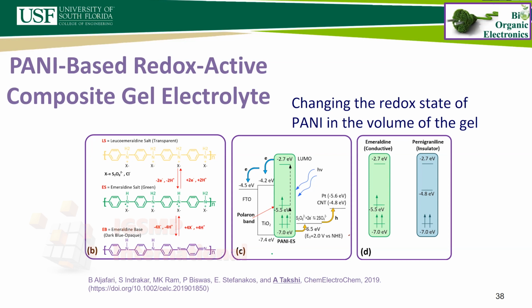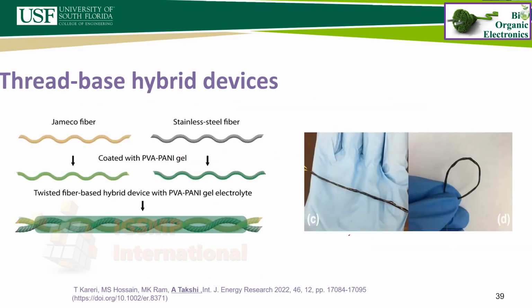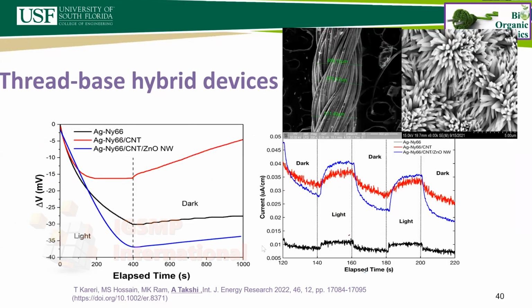So we took advantage of such a feature and said that perhaps we can use it for making wearable hybrid devices. We took that gel and chose 2 different types of conductive threads. We coated them with the gel, and then we twisted them together with another layer of the gel. You can see in the picture at the side that it's a very uniform coating over the 2 threads, and it's even flexible. But having 2 different threads, we now have 2 different electrodes. So we started testing them.